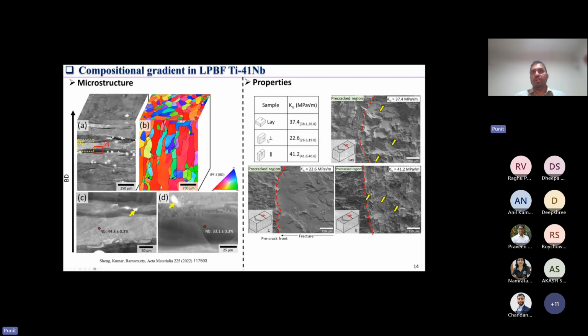And in this case, you can see the crack path would not interact that much with this compositional gradation, the lines of this compositional gradation inside the phase. And you can see here the fracture toughness is around 22.6 megapascal root meter. In the other two directions, the fracture toughness almost doubles.